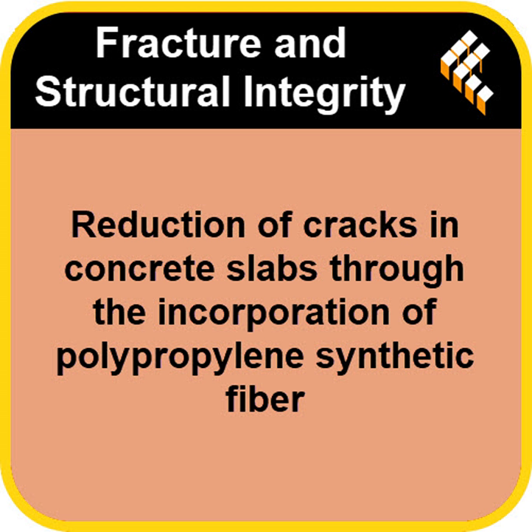Okay, so what about crack length? Stopping a crack from spreading across the slab. This is where it gets even more interesting. Again, DM02 was the star. In fact, it was the only mix that reduced the crack length at all. The only one? The only one. It achieved an 11.46% reduction. Both the light dose and the heavy dose actually made the cracks longer than the control. So the other mixes were failing on two key metrics.